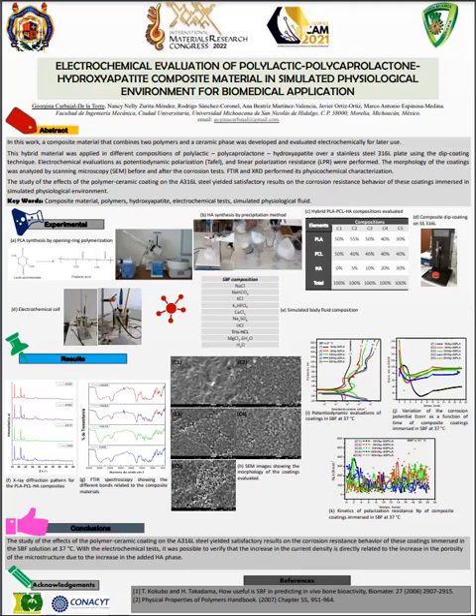Polymers and ceramic synthesis were realized by applying different compositions of polylactic acid, polycaprolactone, hydroxyapatite over a stainless steel plate using the dip coating technique. Electrochemical and physicochemical characterizations were performed. The methodology for synthesizing the polylactic acid was by ring opening polymerization. Figure 1 shows the general chemical reaction. In Figure B, we can observe the hydroxyapatite synthesis where a calcium to phosphorus molar ratio of 1.67 was conserved.